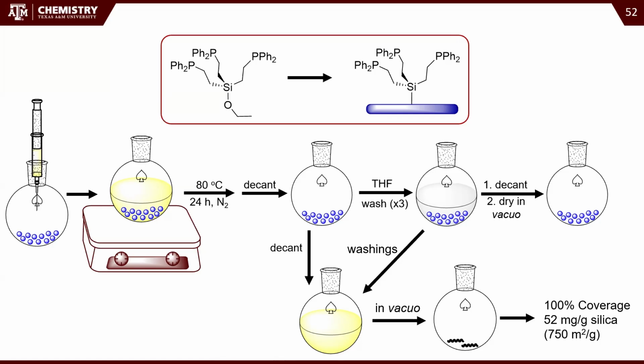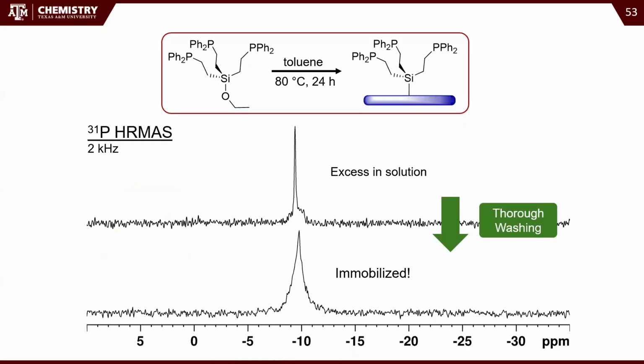Like I said, it's relatively dilute. And this is with the 750 square meters per gram silica, so relatively high surface area. The ligand's just kind of bulky, and oh well. So you can see with HRMAS, when everything is really immobilized, if it's in solution, you get a sharp signal.